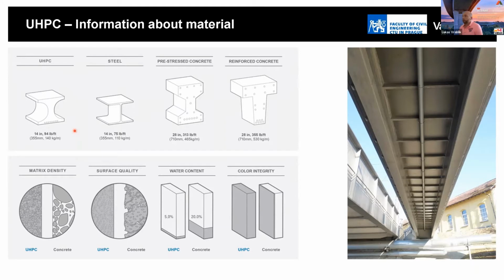As I said, the great advantage of the UHPC is not only from the mechanical point of view, it is also the effect of the closing of the matrix, closing of the volume of the concrete. Again, comparing between UHPC on the left side and normal concrete. This is the aggregate, this is the cement between the aggregate. In UHPC, the matrix is completely closed. In concrete, there are some hollows, there are some spaces, and by these hollows, it is possible that the aggressive water from the environment goes through the structures and could attack, for example, the reinforcement.